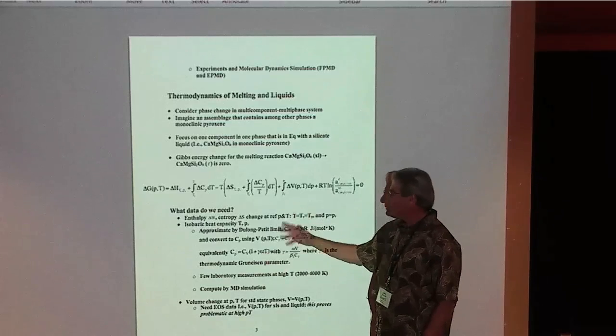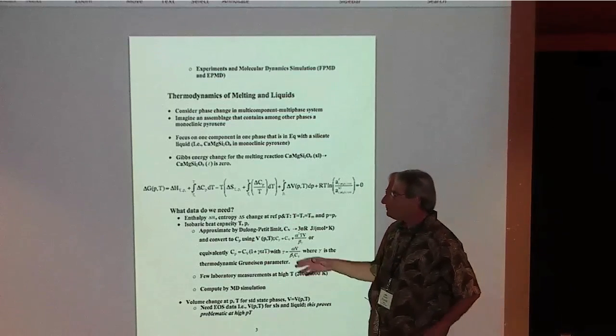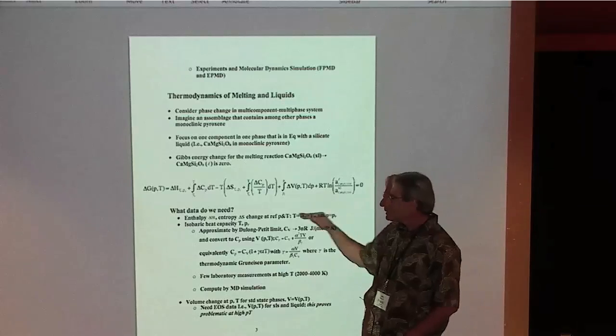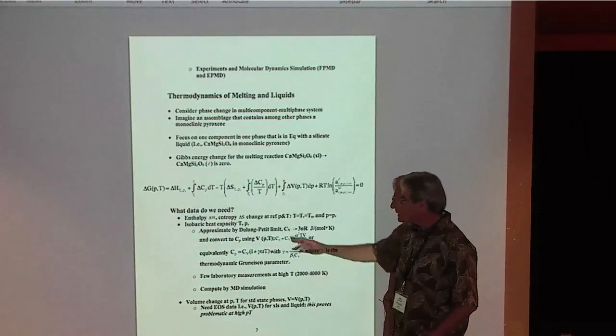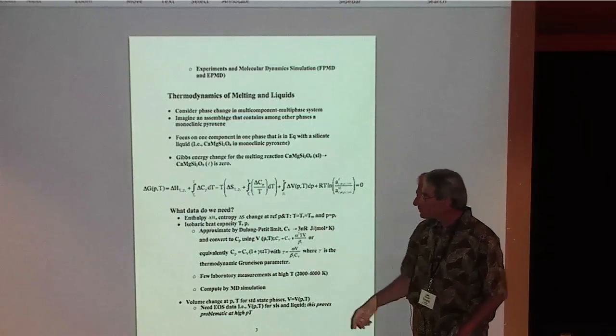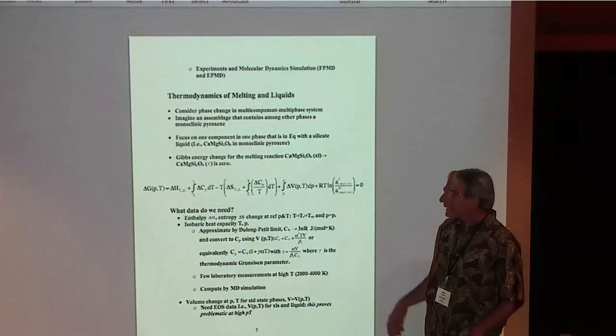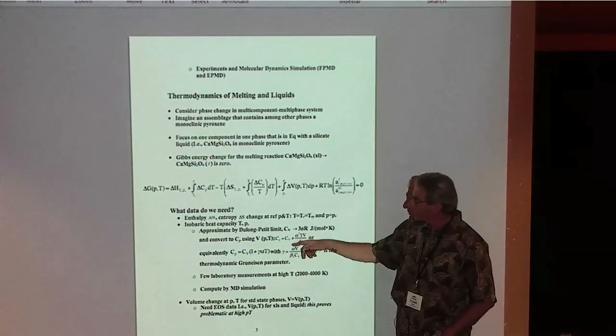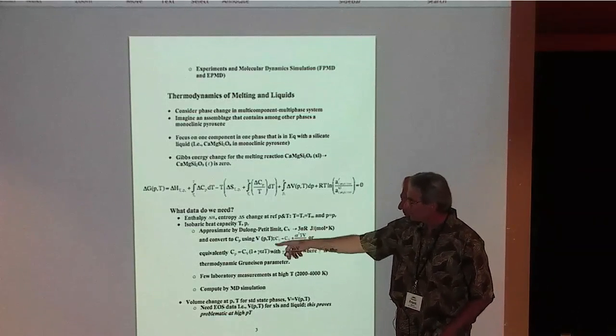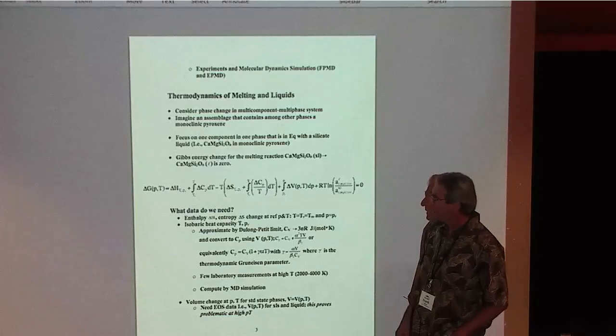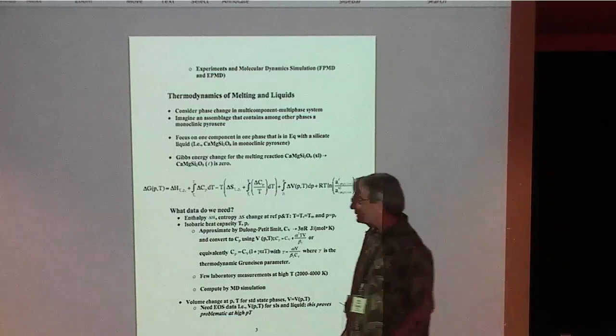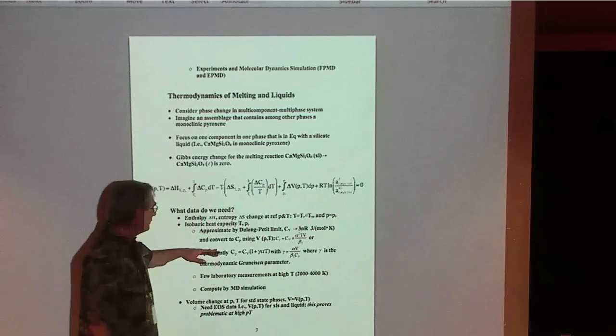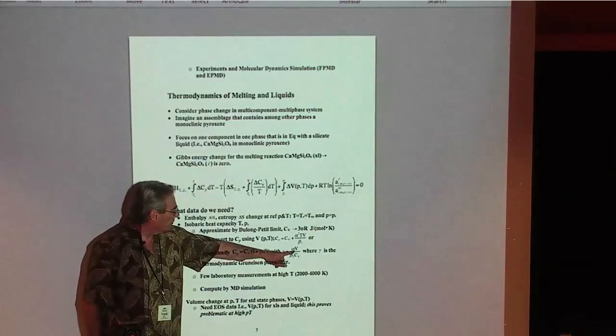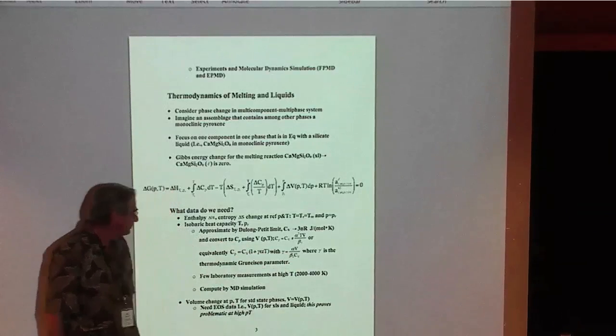And then there are ways you could worry about that. At really high temperatures there are these limits: the Dulong-Petit limit, and the isochoric heat capacity goes to a constant. And then we could use standard thermodynamics to convert this isochoric heat capacity to an isobaric one. This is a detail, but the only thing I want you to pull out of this is that to make this conversion, the volume appears.